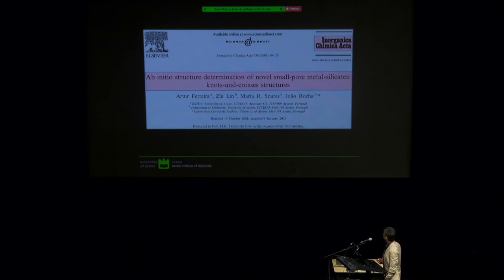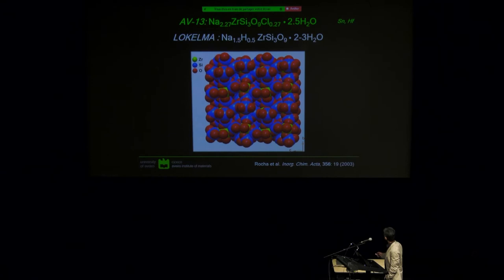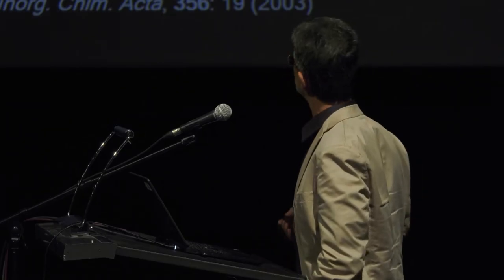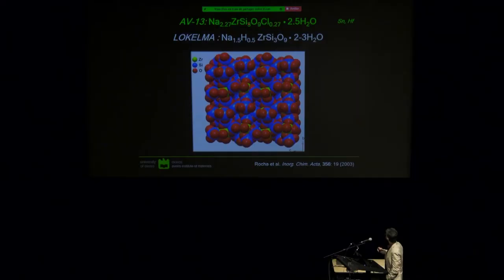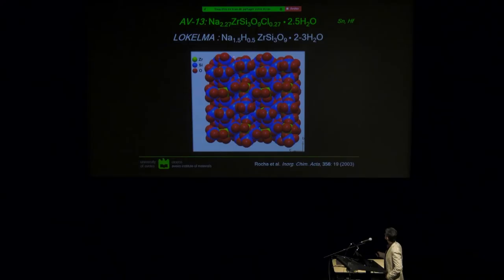We published a zirconium silicate structure, which is the drug. And this is the structure. It doesn't look porous because the pores are very, very small. So it's a sodium zirconium silicate. You can see our material has sodium, a lot of sodium and chlorine, and it's not good for your health. So they preserve the structure, but they modify it in such a way that you do not have any chlorine anymore and you have less sodium. That's the only difference. The structure is the same.